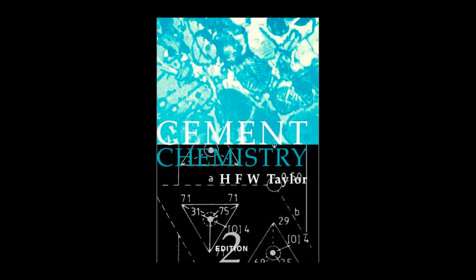Okay, then the CSH itself is divided. It is. You have the inner product, CSH, which is the dense, high-quality CSH gel layer that forms in situ, right where the original clinker grain used to be. It's highly dense because it forms in a very restricted space. I see. And then the other. And the other is the outer product, or the matrix. This is the CSH that precipitates into the original water-filled space. It's often less dense, and it generally contains the products from the hydration of the interstitial phases as well. So that inner product is inherently denser and higher quality because it's so tightly constrained by the shape of the original grain.